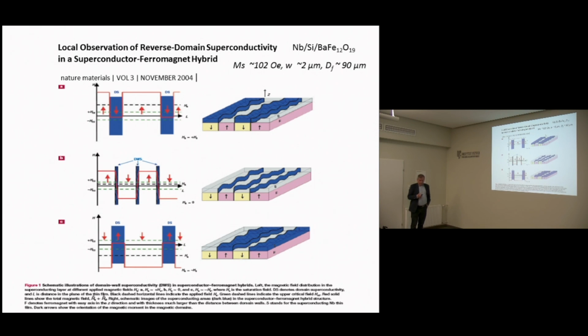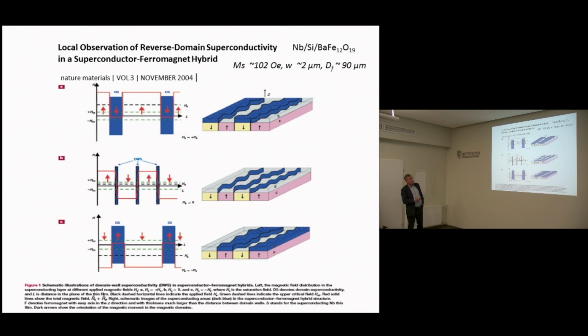So the first paper, as I said before, Professor Ritta Szymczak already published on the domain structure of this system. And presumably they also concluded that this system is very useful to study this kind of behavior because, first of all, saturation is very low. The upper critical field is much higher, so it means that in zero magnetic field there are optimal conditions to study this effect.